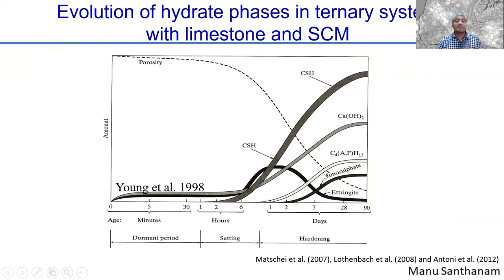Now that's the problem in sulfate attack. What happens when external sulfates come into contact with this monosulfate? They form ettringite, and this ettringite formation in a hardened concrete leads to volume expansions and cracking. That's something which is avoided by the use of this ternary system.